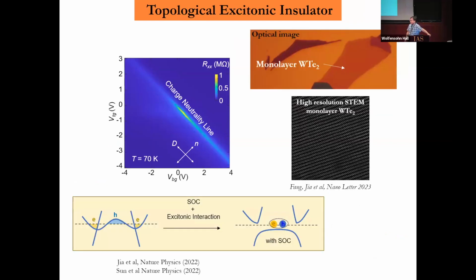Why is the few-layer system semi-metallic while the monolayer is insulating? This is also an indication that interaction is important. In a multilayer, the screening will be stronger, so it's a weaker interaction. It's only in the monolayer and bilayer - the bilayer has much weaker insulating states. In the bulk, there's very strong screening, but in the monolayer, the binding energy is enhanced. So that's part of the reason why it's interaction driven.